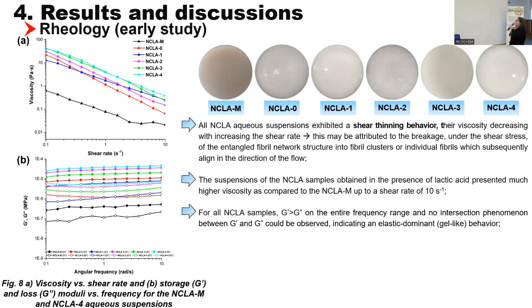We can also see that the viscosity of the samples obtained in the presence of lactic acid is higher than the one obtained in the presence of hydrochloric acid alone on the entire frequency range. This might be due to the slightly higher hydrophobicity of the samples obtained in the presence of lactic acid, which endowed the fibers with a water repellent characteristic, as well as to new interactions between the fibers, maybe of hydrophobic origin. And we can also see that for all samples, regardless of the acid that we use, the storage modulus was higher than the loss modulus, which means that the suspension of the cellulose nanofibers present a gel-like behavior.